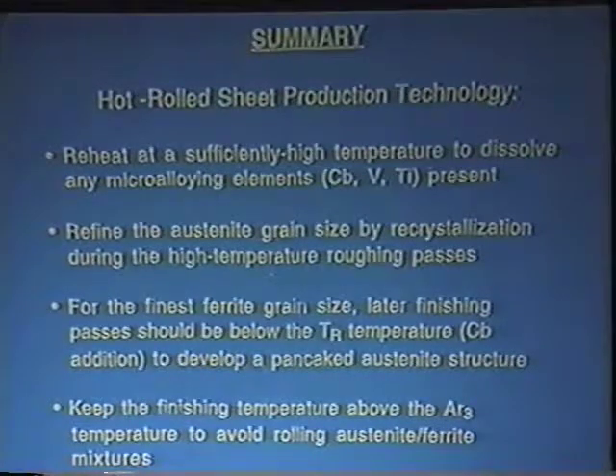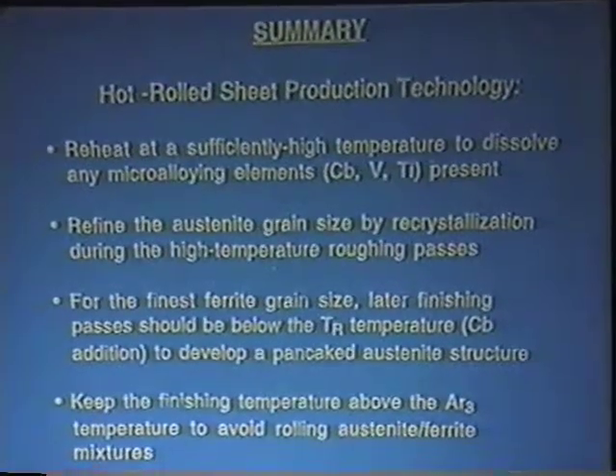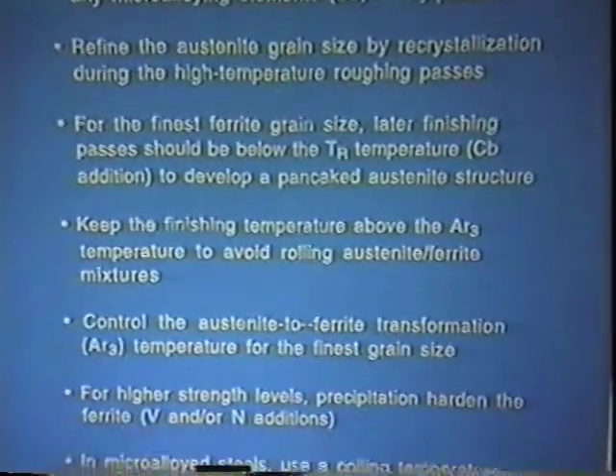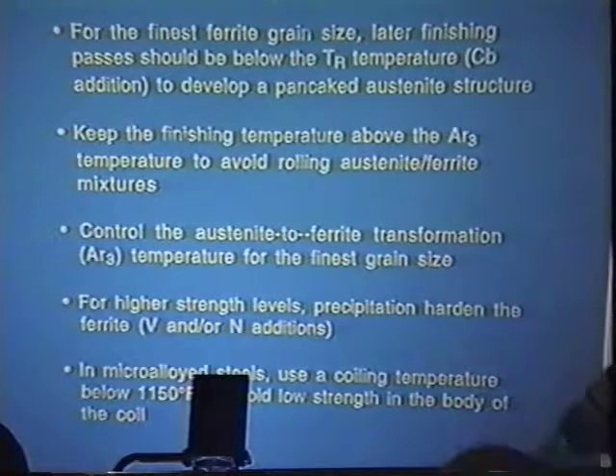The grains are a different shape. I can explain that later. We want to make sure we always keep the finishing temperature, which is the temperature coming out of the last finishing stand, the F7, above that austenite to ferrite transformation temperature to avoid rolling them together. We roll austenitic steel. We've started rolling ferritic steel, which the Europeans do a lot of. We deliberately roll it below its transformation temperature, so you end up with a ferrite structure instead of ferrite and pearlite. You end up with one phase. And that is supposed to provide much more formability, drawability. We're in the experimental stages; we've rolled 4 coils so far.